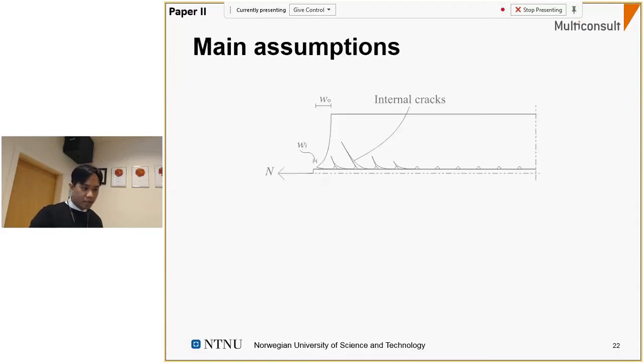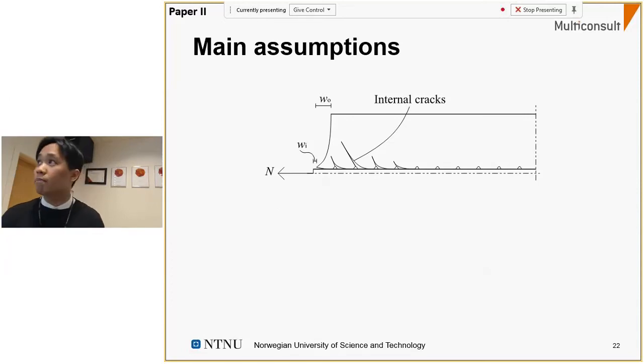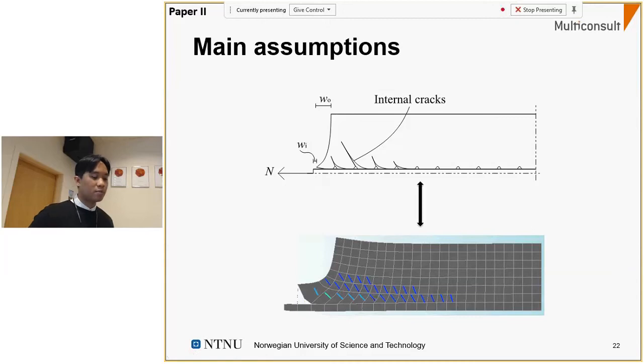So the main assumptions in this finite element model are based on the behavior that is observed from the experiments conducted on such concrete elements. We saw earlier that due to the rib interaction between concrete and steel, internal cracks form, and the concrete at the steel-concrete interface follows the displacement field of steel almost completely, which means that the crack width at the steel interface level is much smaller than the crack width at the concrete surface. Now, in our analysis, we neglect the crack width at the steel interface, assuming that the concrete follows the displacement field of steel completely. This can be seen in that the shared concrete nodes and steel nodes have the same displacements.